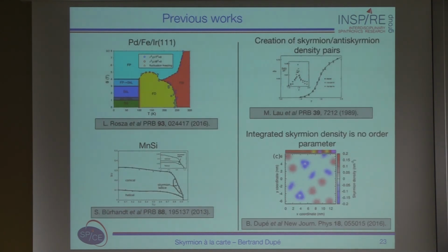So here is the previous work that I selected, non-exhaustive, on the temperature dependence of some systems where you have skyrmions. On top you have palladium iron iridium 111. This is the first paper which published the phase diagram in 2016. And you see that as you increase the magnetic field, the transitions between the different regimes are perfectly perpendicular to this critical temperature.